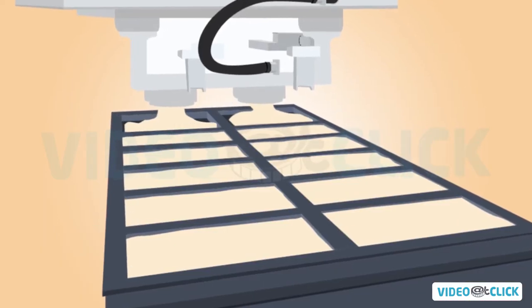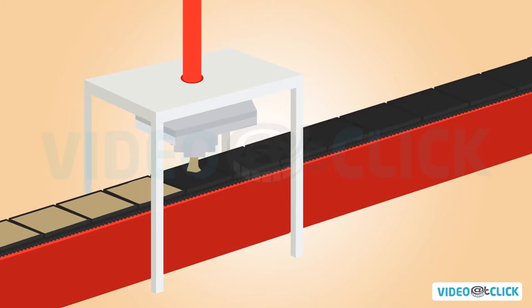Material dispensed from a mixer feeds a secondary dispensing hopper. Block paving moulds are large moulds containing individual block moulds, rather like a large ice cube tray. The dispensing of the semi-dry mix requires vibration to allow the mix to fall evenly across the mould as it will not flow like wet concrete would.